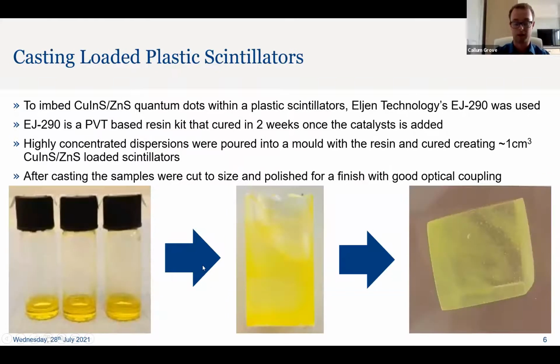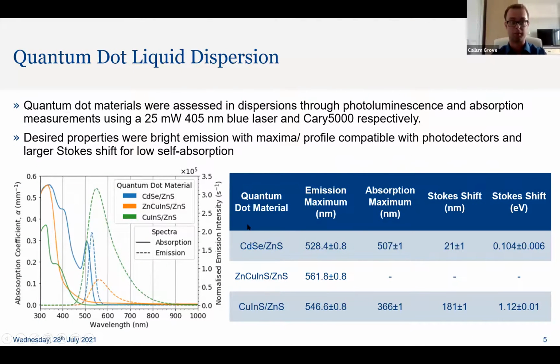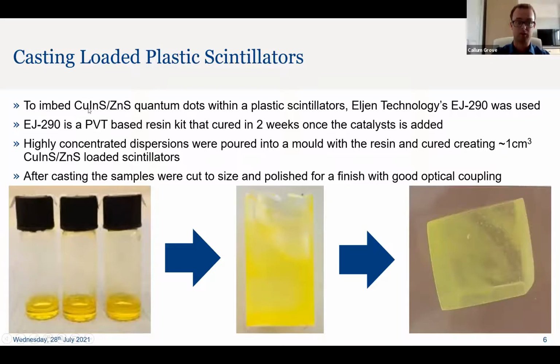So moving on, we selected the bright and high Stokes shift copper indium sulfur for loading into plastic scintillators. The idea behind this was that we would take Eljen's EJ-290, which is a casting resin. It's a PVT base with a mixture of fluors in a partially polymerized resin. Then you add a catalyst and you can turn it into whatever shape you want, or load it with whatever material you want to load it with, and then cast it in a water bath at about 50 degrees over a period of 2 weeks.